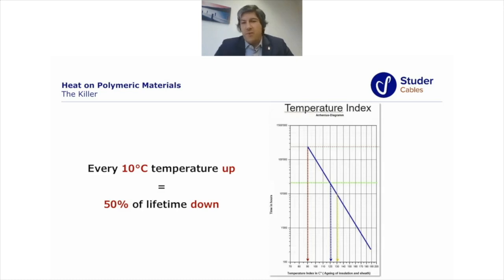In the polymeric materials which we use, the typical Arrhenius curves shows us that by the temperature of 120 degrees, the polymeric material would be able to withstand for 20,000 hours. If I would increase the temperature by 10 degrees, then immediately I drop it by 50%, means up to 10,000 hours. And this is very important because heat caused by the resistance in PV is one of the very frequent phenomenons. And I would say extended heat exposure is something what we see in PV very, very often.